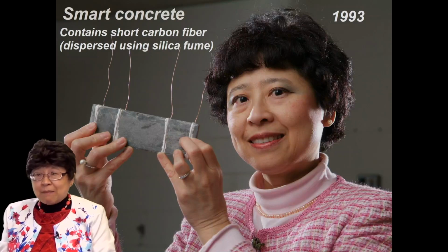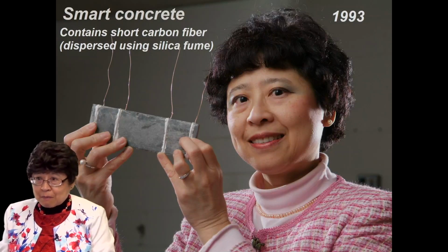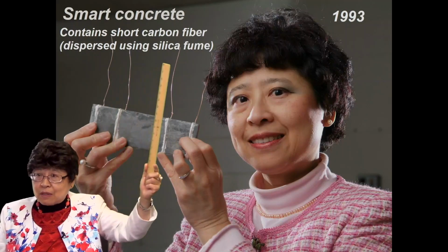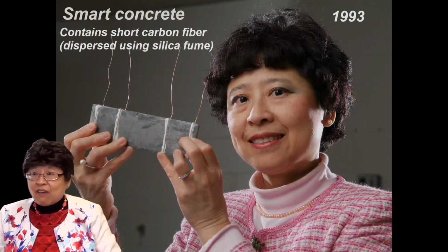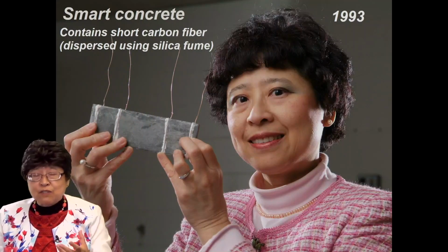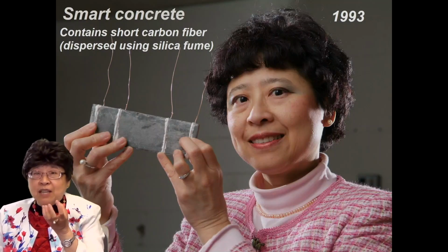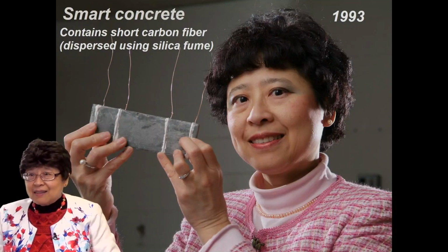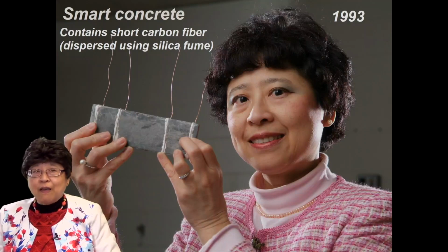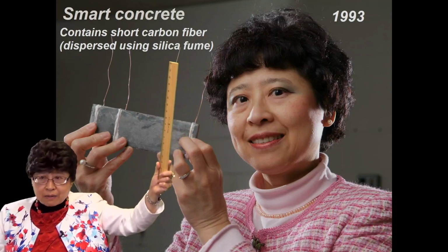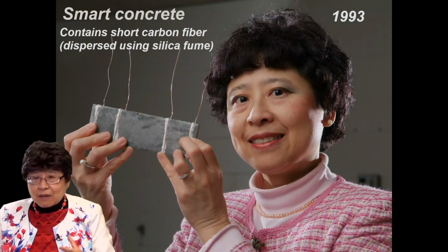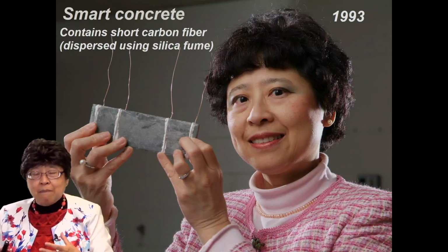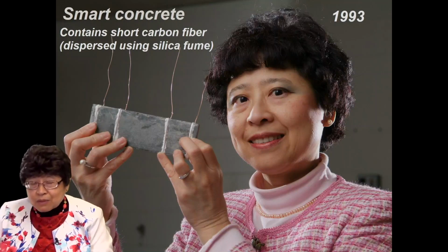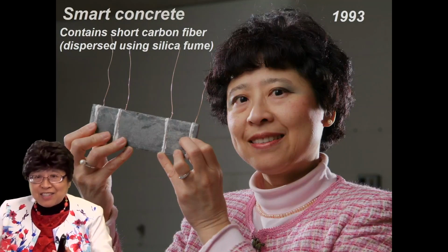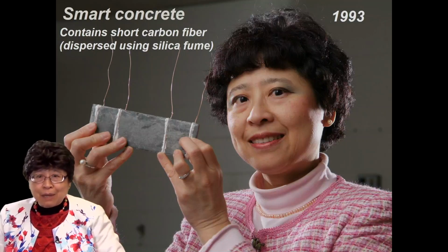Now, it's not just a matter of throwing some short carbon fiber into the cement mix. One has to disperse the fibers very well. And these fibers are microfibers, a diameter of the order of 10 microns. And they tend to clump together like bunches. And to disperse the carbon fiber, it's very helpful to throw into the cement mix silica fume, which are submicron particles mostly. And because of these very tiny particles, their presence in the mix during the mixing, the whirling around of the mix, just mechanical action, it loosens up the fiber bundles.